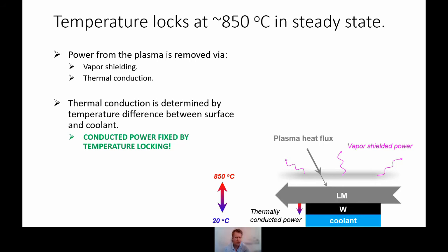because you can easily destroy your sample if you put too much power to the coolant. So you can imagine maybe water will heat up, especially where the plasma hits. And if it starts to boil, if you put too much heat, at some point you have boiling to such an extent that you have zero cooling anymore and your component will just fail. So this is actually a great way to try and avoid that mode of failure.